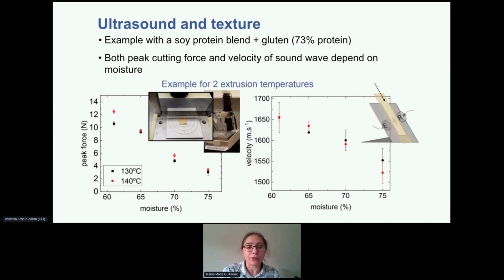We did that with different things, but what I will show today is an example with soy protein blend and gluten. It has 73% protein content. And we measure the peak force in the lab, and we measure the ultrasonic signal. What I'm showing you is that the peak force changes with moisture. So basically, when you increase the moisture, the force needed to cut the material decreases. It's a bit easier to cut.